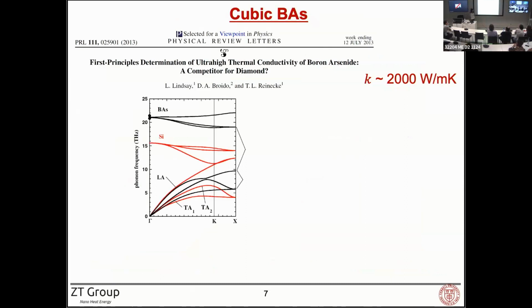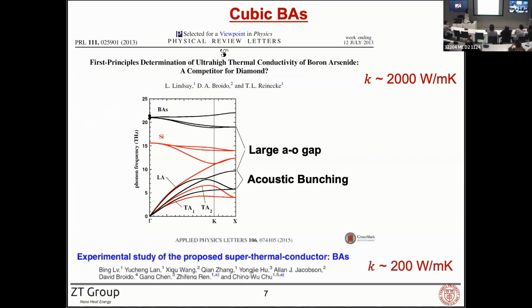So if we compare boron arsenide in black with silicon in red, we can see there is a large acoustic and optical gap that limits the scattering between acoustic and optical phonons. And the three acoustic branches are close to each other, the so-called acoustic bunching. So that limits the acoustic phonon scattering. So essentially, this limits the three phonon scattering process and gives the high thermal conductivity.